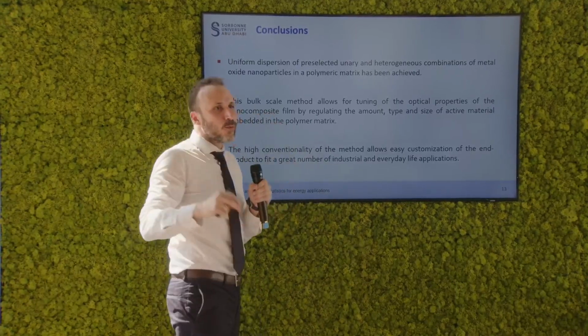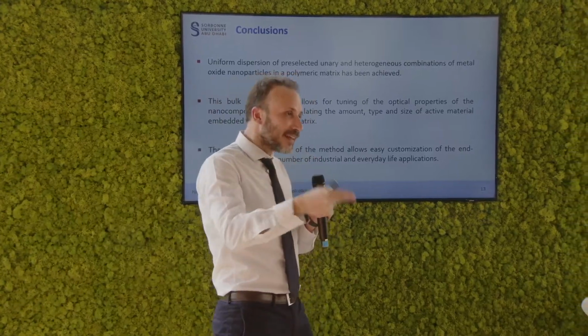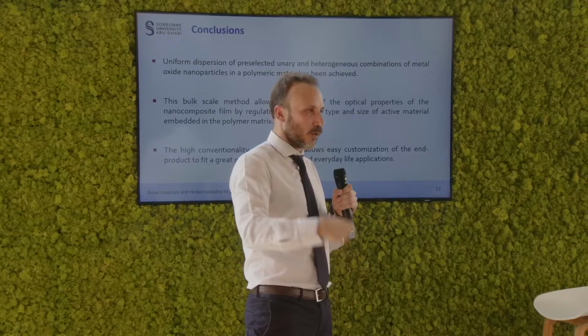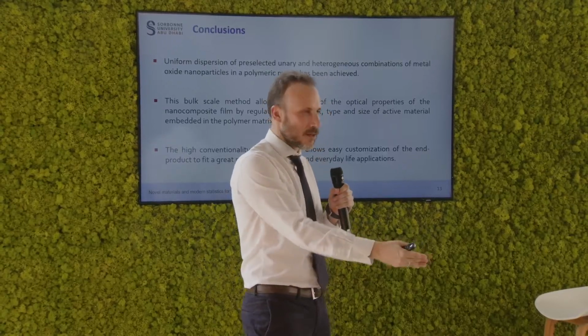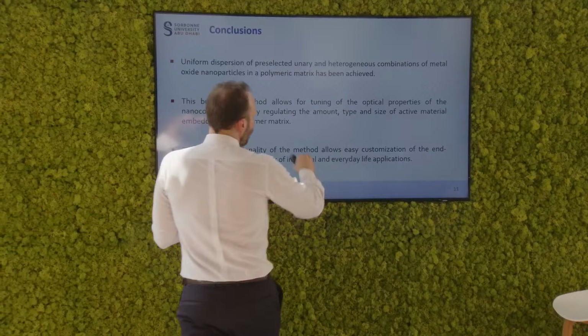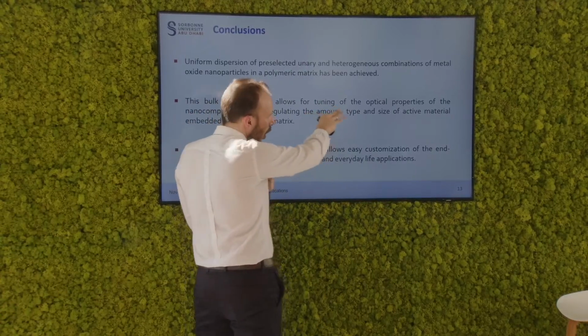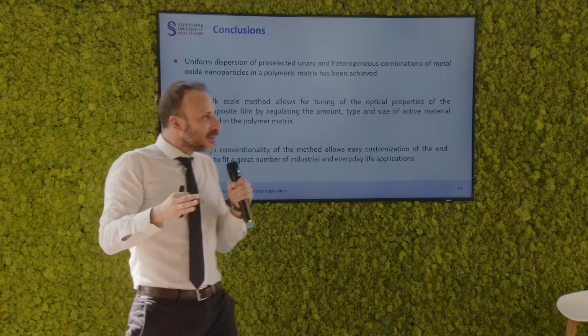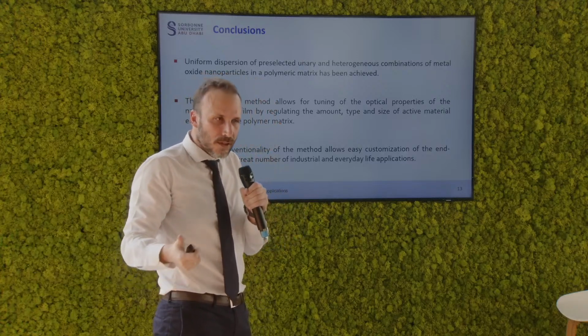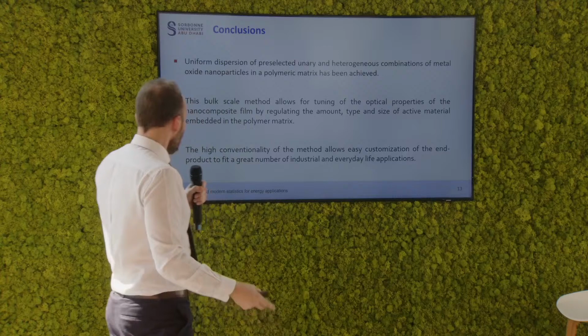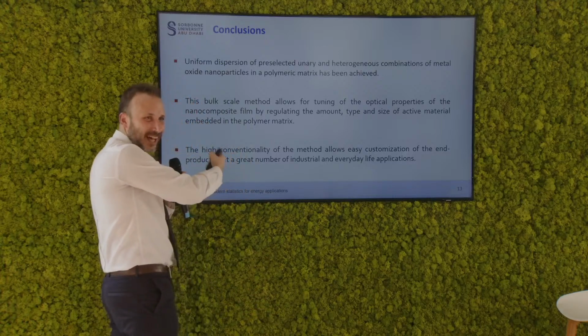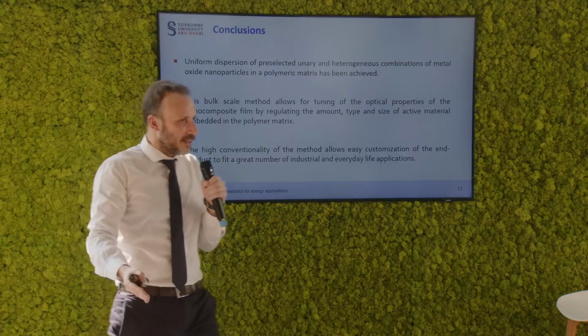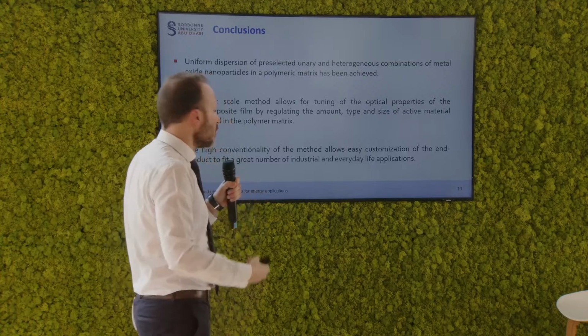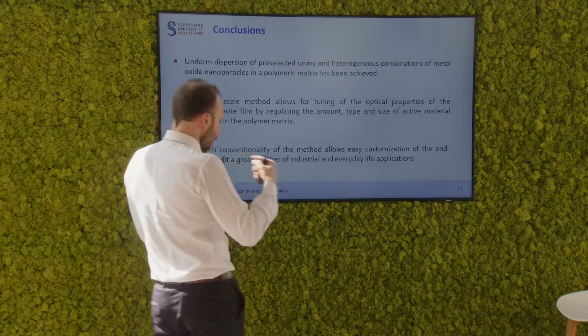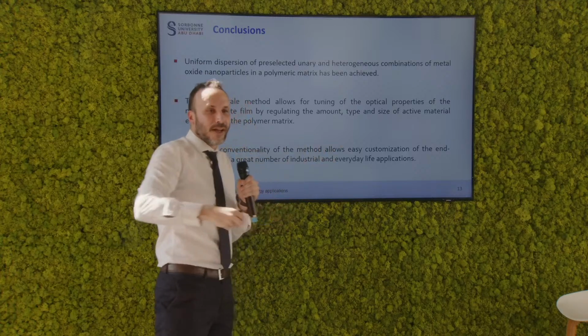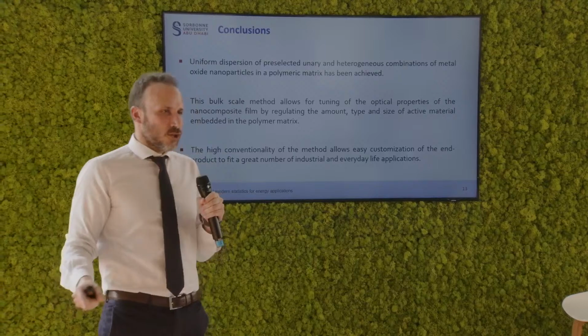The bulk scale method that we're using is both cheap, efficient, and it can produce large quantities of samples. So it can be used either for everyday or for industrial uses. At the same time, it's the same method that is allowing us to tune the optical properties by simply regulating amount, size, and type of the particles. This is a very conventional method. It's been used for many years, so it is very well known. It's very well established, which means you can use it extremely easily. And in this way, we can customize the final material depending on the applications that we have in mind.